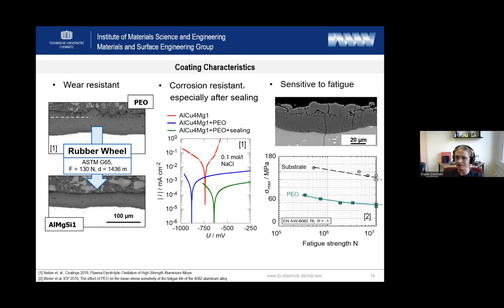And now let's speak about fatigue wear. Here it needs to be stated that PEO coatings are sensitive to being damaged by continuous alternating mechanical stresses, which is caused basically by the ceramic nature of the applied coating. And we know ceramics are brittle and tend to crack. And if such a crack starts to grow, the excellent substrate bonding of the coating supports a transmission of the crack into the substrate.